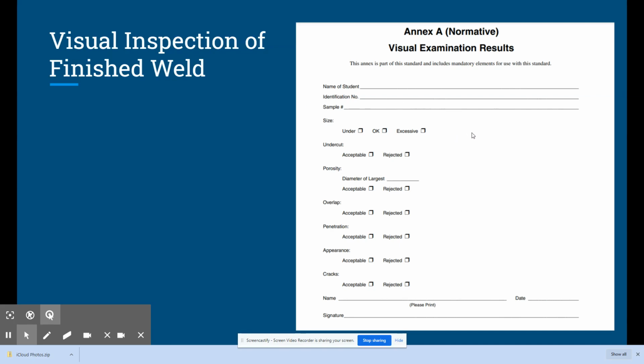So like a fillet weld, if it calls for a minimum size, we want to check that. Undercut, is it acceptable, rejected? Porosity, diameter, the largest pore, acceptable, rejectable. Overlap, if there's any overlap, it's unacceptable, it's rejected. Penetration, we can't necessarily measure penetration, so that one gets skipped. Appearance, this is where the inspector kind of has a little bit of input in their opinion on the appearance of the weld.